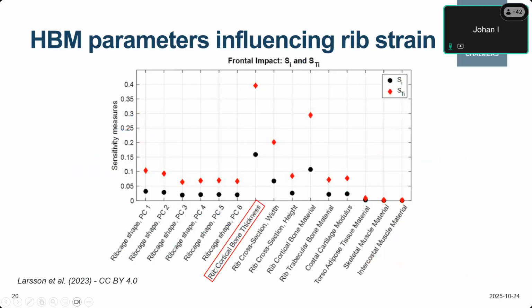The first one is the rib cortical bone thickness. And again, we have varied all the parameters according to what is seen in the population, so they should be comparable. The rib cortical thickness is actually the most important one here. This is a sensitivity index, so the higher that is, the more important the parameter is.